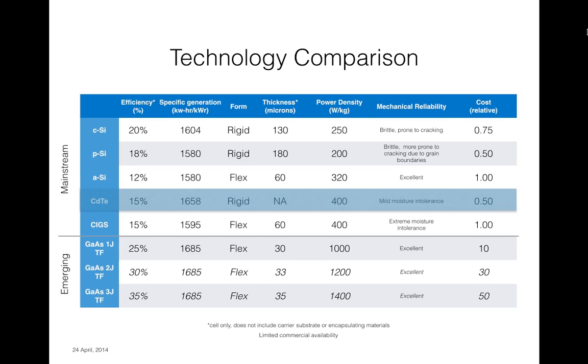And so what we developed at Alta was a way to create these very thin single junction and dual junction solar cells, and had demonstrated commercial efficiencies in the single junction case of almost 29%. And some of the examples I'll show you later that are public domain, we're using 25% devices. And those we could produce pretty much commercially all day long. And then we had pioneered a two-junction device that was nearly 31% efficiency, which the company believes can commercialize at 30%. And so you could see that there's a pathway now to increasing solar cell efficiencies dramatically and delivering properties that are much better for the application than had previously been devised.